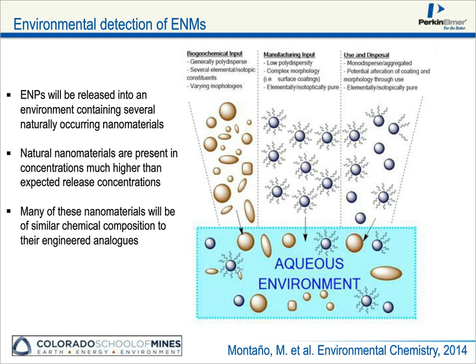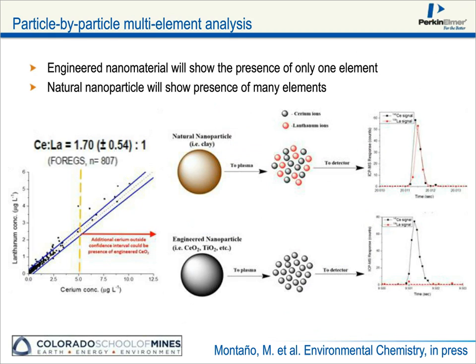So one thing we can focus on, just as an example, is looking at cerium and lanthanum in the environment. I have a cartoon on the right that shows that if I have a natural particle, we might have both cerium and lanthanum ions in the particle. If we introduce that into the single particle ICP-MS and we could track both elements, we might see a signal, that pulse, that shows both elements. In contrast, an engineered cerium oxide might be isotopically pure, and therefore we would not see any lanthanum, we would just see cerium. Now, if you look at the left, that's a data set from the European database that shows on the order of about 800 samples of stream waters that show there's a fairly tight distribution between cerium and lanthanum in nature. So again, we would expect that if we could look at the composition of the particle on a particle-by-particle basis, we might be able to start to tease out, to some degree, the presence of these two types of populations of particles.